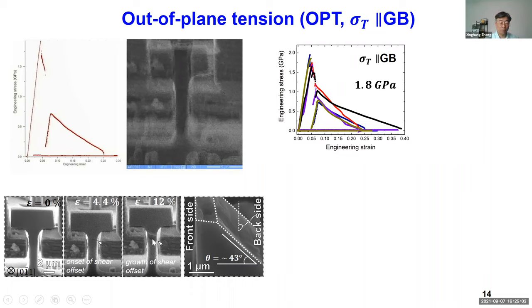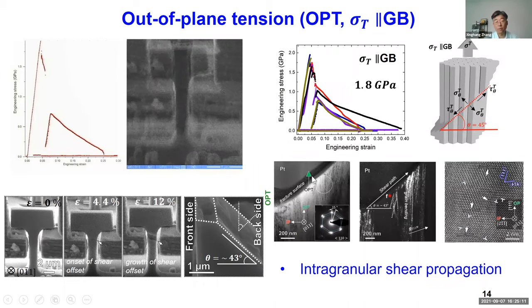When you look at this fracture surface, it's close to a 45 degree angle shear band. And from microscopy, we see quite a bit of intragranular fracture, and this is the shear fracture surface. But when you do high resolution TEM, you do see some kind of dislocation events within the grains.